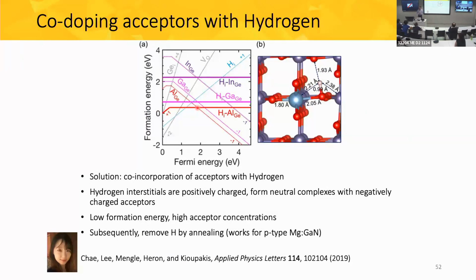And there's some very recent work on p-type aluminum nitride, or AlGaN alloys, where people see some remarkable conductivity at very high aluminum content through the incorporation of an impurity band of magnesium. So I'll be happy to share more work with you later about how high concentrations of magnesium give rise to dopants that can be activated at room temperature, much lower than what we expect based on the activation energy. So yeah, impurity bands may help us here.